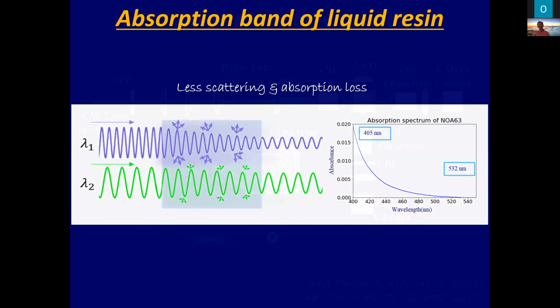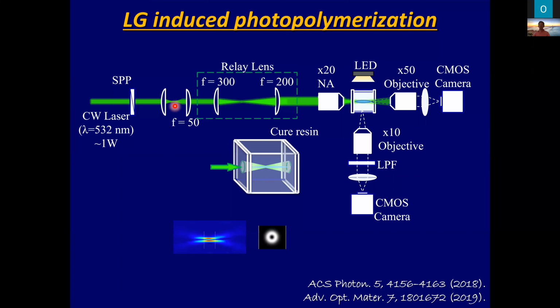This is the experimental setup. We prepared a very simple experimental setup. A 532 nanometer green CW laser. The laser beam is converted into the vortex mode by using a spiral phase plate. Laser power is roughly 1 watt. Okay, the vortex mode is directed towards the cell, containing the liquid phase resin, by relay optics. Photopolymerization is observed by a CCD camera from the side view. This CCD camera can record the growth of the fiber inside the cell. We also want to observe transmitted light from the fiber waveguide by using a conventional CCD camera from the top view. Okay.